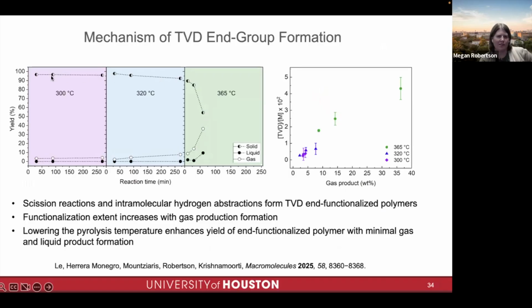If we go down lower, say 300 degrees, now more than 90% of what's produced is still a polymer. It's a solid, and very little liquid. That's almost negligible, and maybe 5% of this product distribution is gases.